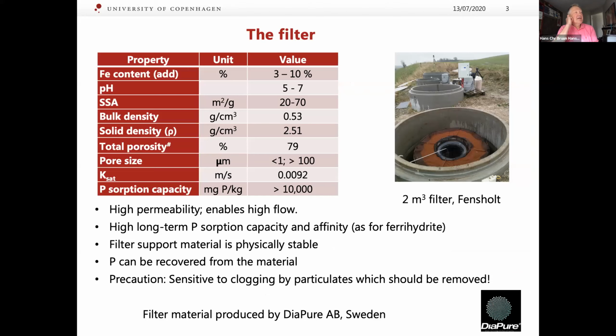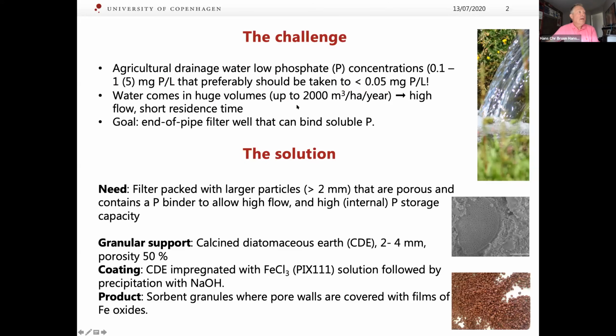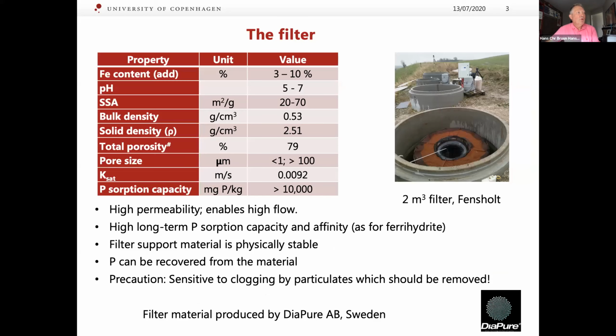So we get this material, we load it with 3 to 10% of iron. It has a specific surface area in the range here of 20 to 70 square meters per gram. It has a very high porosity, so for the whole filter, it's about 80%. Pore sizes are in two classes. There are very small pores, but also a fraction of a bit larger pores. The permeability, you can see here, the hydraulic conductivity is high. So we are now testing it in a field here for agricultural drainage water. The permeability is high, so it enables high flow.